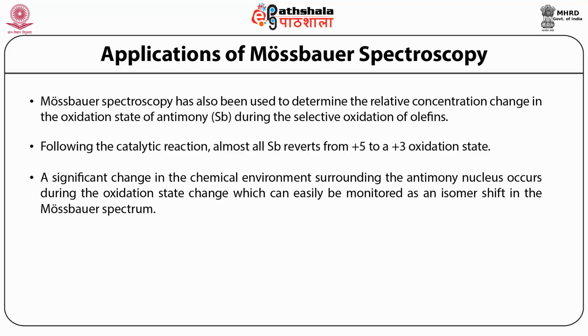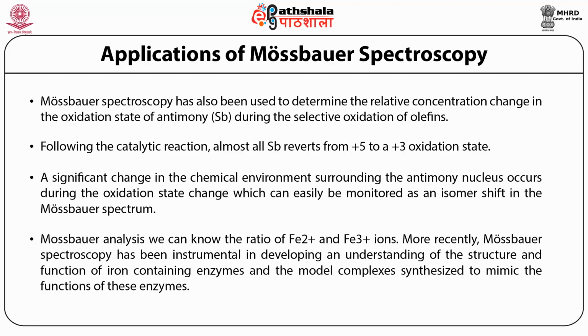In synthesis of ferrite, sometimes ferric converts into ferrous during the sintering process. If ferric converts into ferrous, that deteriorates the magnetic character of ferrite. So basically, quality of ferrite is judged from the ratio of ferric and ferrous. If the ferrite sample consists of more ferrous, it is inferior ferrite. If our ferrite sample consists of maximum ferric ion, then it is good quality ferrite material. So by Mossbauer analysis, we can find the ratio of this ferrous and ferric.